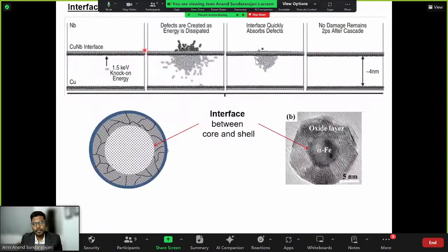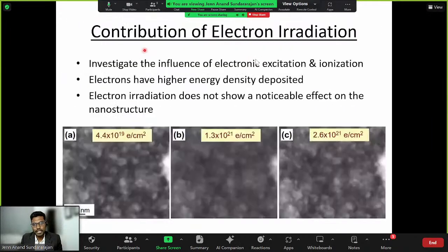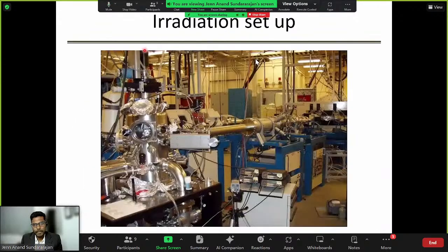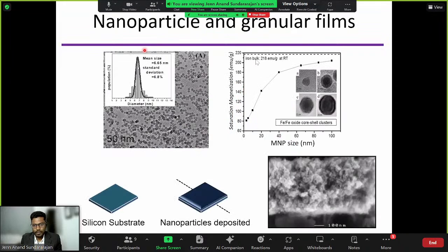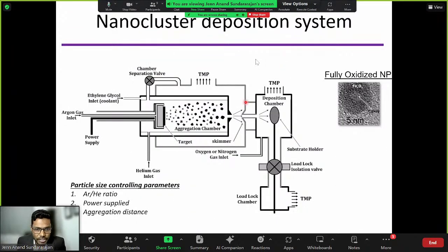Okay, that's a very good question. So, what we do is we sputter these, but actually I can go back to the slide here to explain. Basically, when we create these nanoparticles, we sputter it. Okay, here is the image that I want to show. So this is the target iron, and then we sputter it, and it causes the iron atoms to be released from the target. And as they travel through a pressurized chamber, they aggregate together to form the nanoparticles. This nanoparticle doesn't have any shell, it's just pure iron.